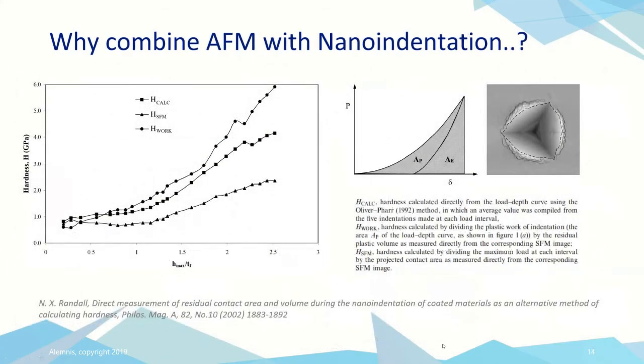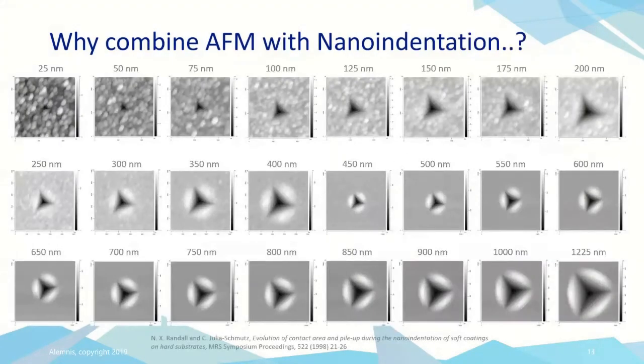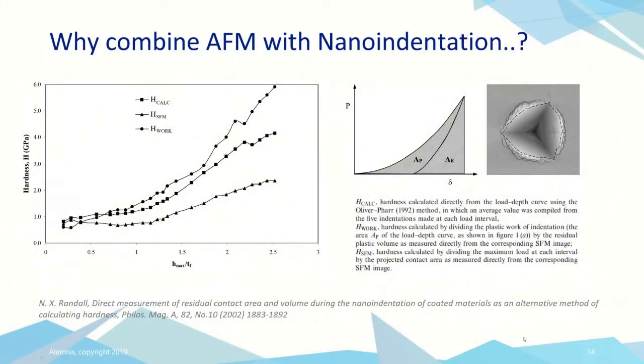Okay, now, one thing from these indents on coatings is to highlight how we can use AFM data combined with the nanoindentation data to calculate hardness in different ways. We're all familiar with calculating hardness using the Oliver and Pharr method, which is basically the accepted method now for getting data from the load depth curve. So from those indents that we just saw, we can plot H-calc. This is the hardness from the load depth curve, but that doesn't take into account any pileup or sink-in around the indentation. So there are other methods which can be used.